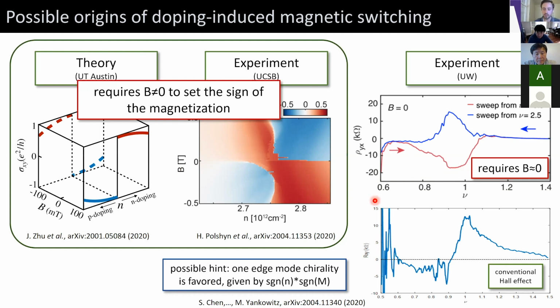And whether this actually turns out to be something that's generic across different samples, or something related to disorder in these samples or disorder in this sample in general, remains to be seen. But we think that we've taken care of measuring all of the confounding variables, and this at least seems to be a robust effect in this sample. And so one possible hint may be that if we subtract off the anomalous Hall component to just get the conventional Hall effect sign, what we find is that the Hall effect changes from electron-like to hole-like across filling.